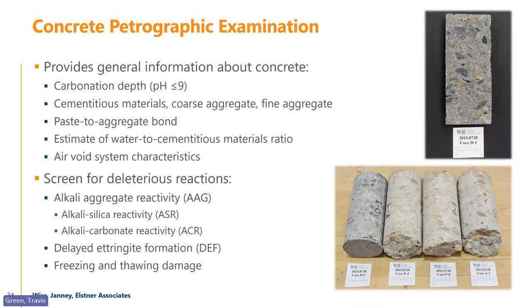We also do petrographic analysis, right? That's a common thing we do. What does that get you? It gets you carbonation depth. Carbonation, when it gets really deep, can produce corrosion in reinforcing steel, and carbonation plus chlorides can produce even higher corrosion rates. It'll tell you about the cementitious materials, of course, aggregates, fine aggregates. It'll tell you a little bit about paste to aggregate bond, water.